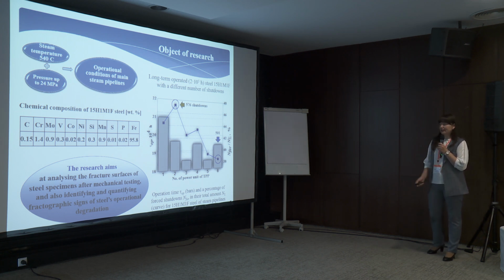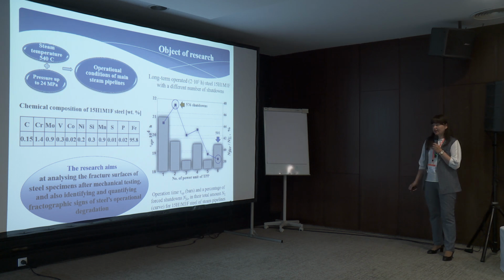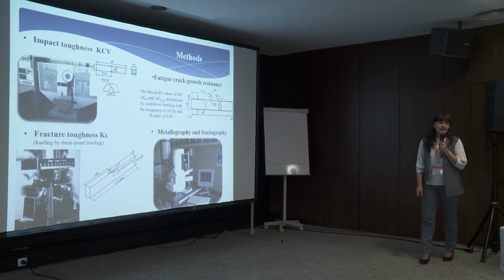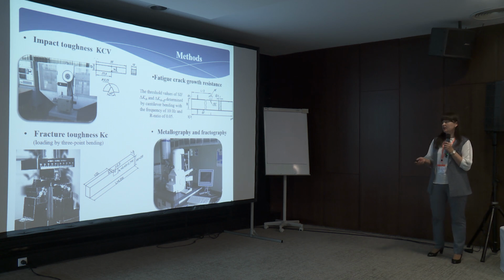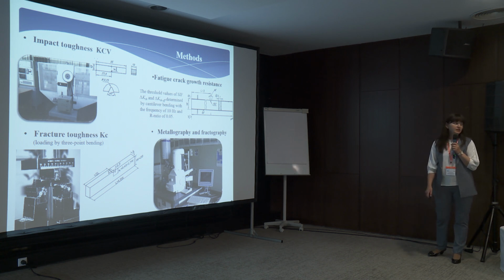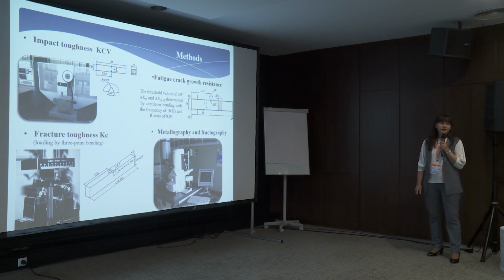The research aims at analyzing the fracture surface of steel specimens after mechanical testing and also identifying and quantifying fractographic signs of the steel operational degradation. To assess the operated steels, we used the following characteristics: impact toughness, fracture toughness by three-point bending, and fatigue crack growth resistance. The threshold values of stress intensity factor range are delta K_th effective and delta K_th. The structural signs of the operated metal and fractography peculiarities of the tested specimens were evaluated using scanning electron microscope.